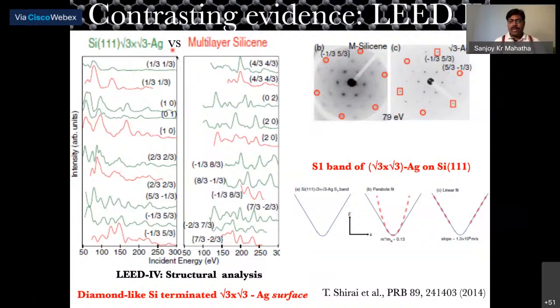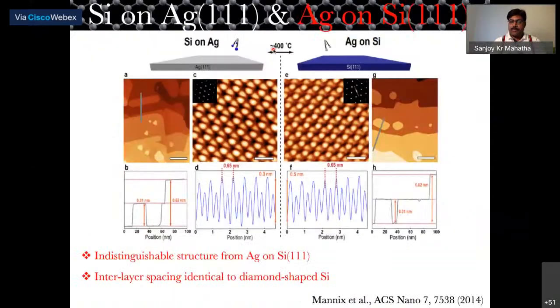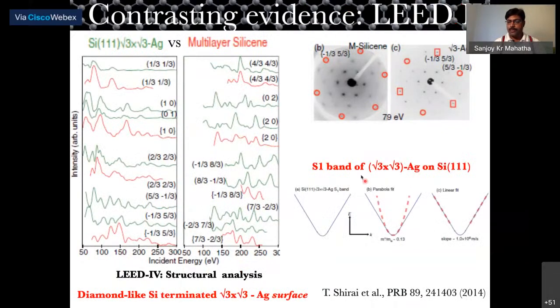At the same time, they said maybe this multi-layer silicene can be synthesized in a very small temperature window, because they could not explain the S1 band they claim near the Fermi level. They could not fit it with a parabola or with a linear dispersion, so they said maybe there is a signature of multi-layer silicene which can only be synthesized in a very narrow temperature window.